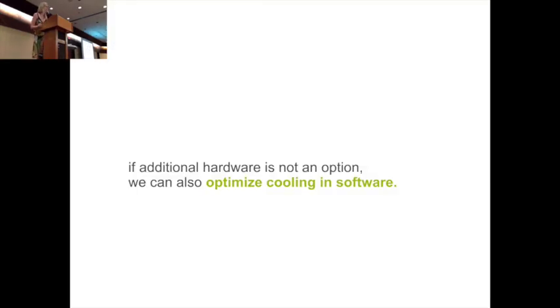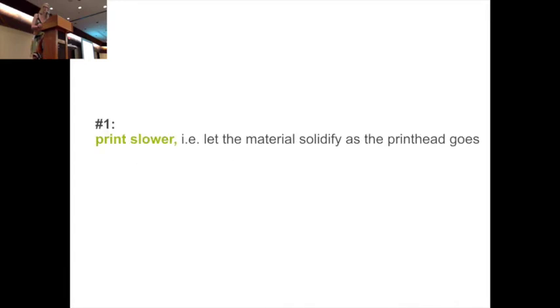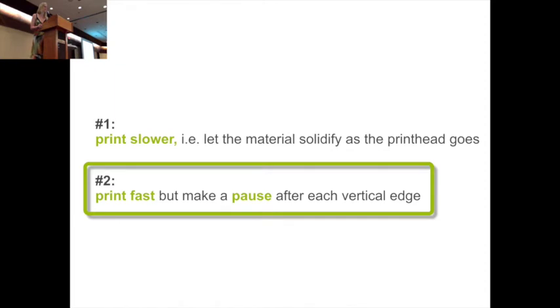If additional hardware is not an option, we can also optimize the cooling in software. There are two options. The first one is we can print slower and let the material solidify as the print head goes. And then the second option is we can print fast but we make a pause after each vertical edge. And surprisingly, the pause actually works best.